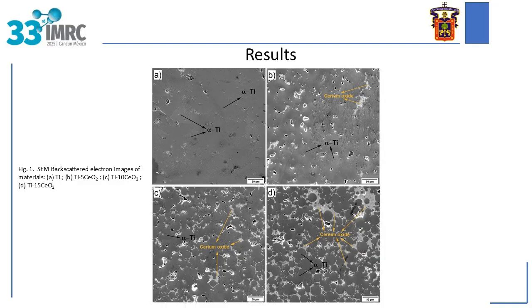In the samples with 10 and 15% ceria, it was observed that titanium particles did not fully coalesce in several zones. This was likely due to the ceria occupying the grain boundaries and pores. However, due to the amount of ceria used, ceramic particles formed barriers between the metallic particles. It was determined that the sintering process was incomplete, remaining in the early phase of neck formation between the particles. These observations are based on the previously mentioned observations of the behavior of ceria in the microstructure and behavior of metallic particles during sintering.